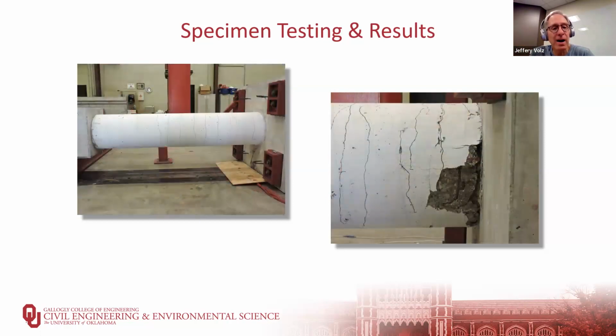Those black lines on the column are cracks in the concrete, right? The concrete is weak in tension. It's going to crack in tension. Since we're pushing it and pulling it in both directions, you're going to get cracks on both sides, so you get these transverse cracks. Nice spacing on the cracks, about 6 inches on center. Great behavior. On the right is where we've increased the cycles even more.